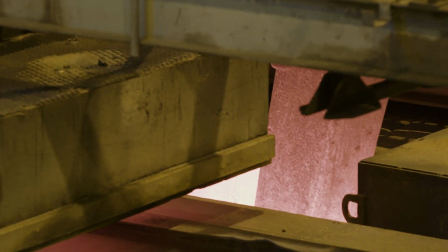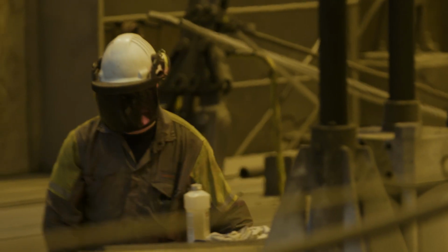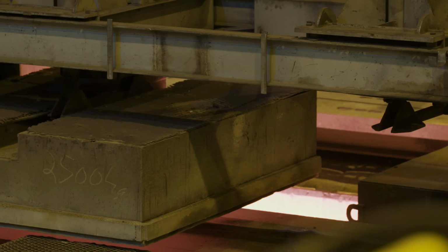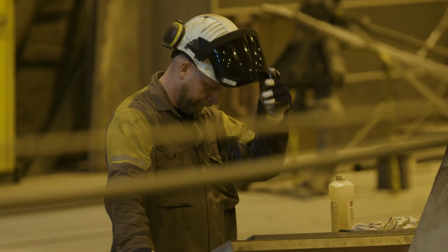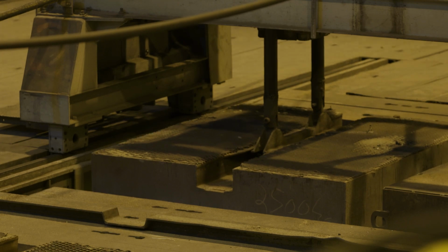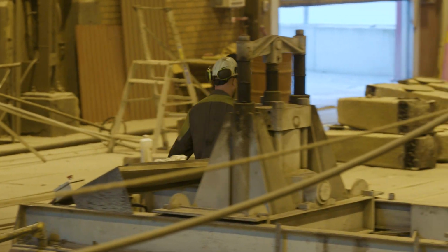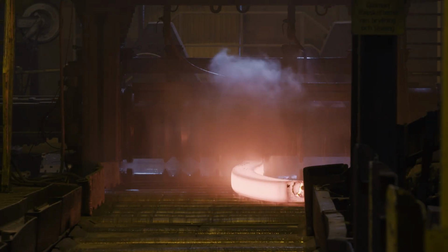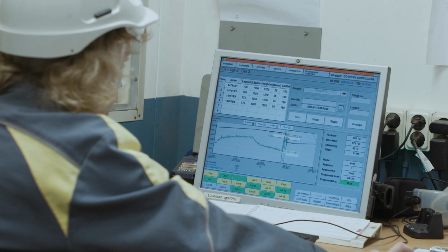The main challenge is to heat the ingots to an even temperature, slow enough or fast enough for the material. If you heat too fast, they might crack, or if you heat too slow, it might get a structure that's not favorable. That's when it's good to have electric heating. In only 20 minutes, you can regulate the temperature in the furnace with about 100 degrees.